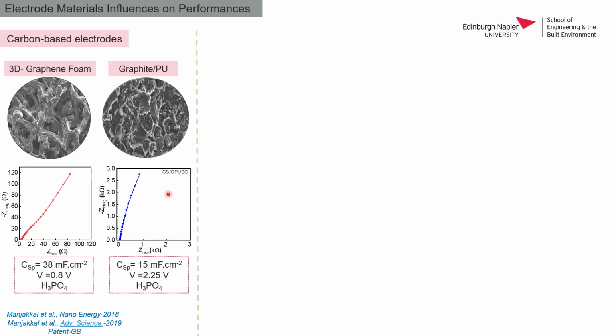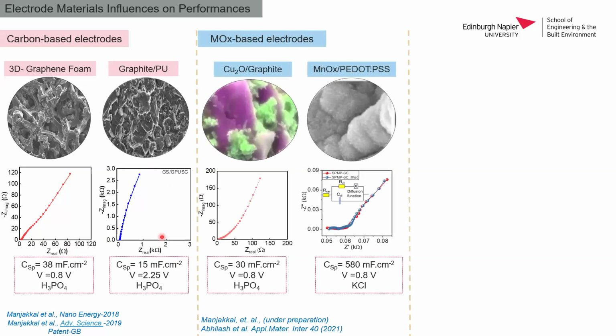And in another case where I developed a graphite polyurethane, there is a thick film based paste, and the electrode configuration here is different, and that cell configuration changes the voltage. And I also got another gel based electrode here, and in a graphite polyurethane composite I got a different performance, which I reported in 2 other papers, and one is in a patent.